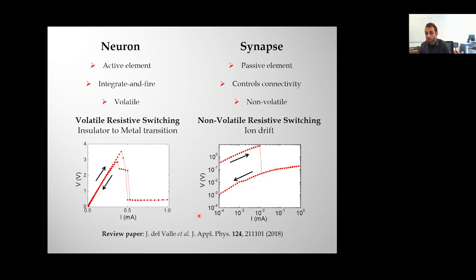So probably the way that more people are working on to try to search for neuromorphic materials is based on a phenomenon that is called resistive switching. Resistive switching is an effect in which you apply an electric field to a material and you can change the resistance of the material. And very conveniently, there are two types of resistive switching. There is volatile resistive switching that you can observe in materials that have an insulator to metal transition. And there is non-volatile resistive switching, which is a completely different phenomenon, and it happens because of ion drift, because you can actually move defects or charged ions when you apply very strong electric fields.